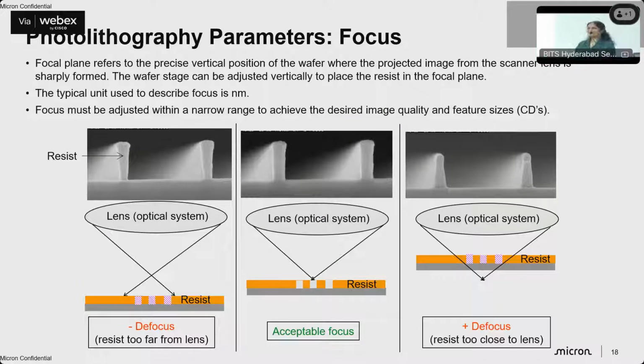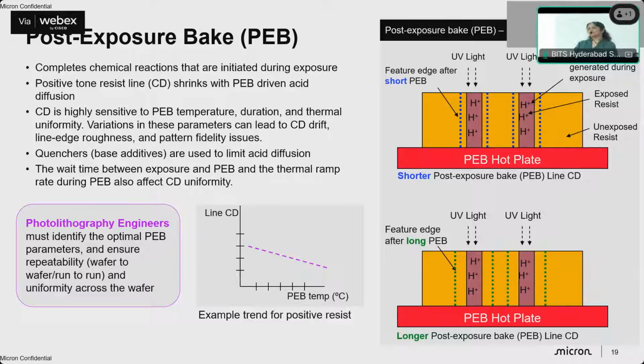There are various parameters to consider if you draw a cartoon, then to actually make it functional. I'm going to list a couple of them. First one here is the focus. So you have to focus correctly. And I'm talking about nanometer scale changes here, 10 nanometers only. A little bit of offset of the focus from the lens to the top of the photoresist substrate is enough to change the profile. And essentially, you change the capacity of the photoresist to function as intended by changing that.